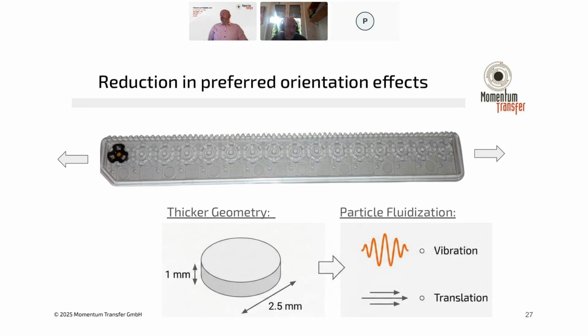But the other thing is that we also fluidize the powders in these wells as well. So during the measurement, the sample holders are vibrated to actually move the powder around in the well, and the whole sample holder is translated back and forth in the beam so that your X-ray beam scans along different regions in the sample. We're actually developing a further spinning device to further randomize the samples in the beam as well. And so hopefully that will be ready towards the end of the year.